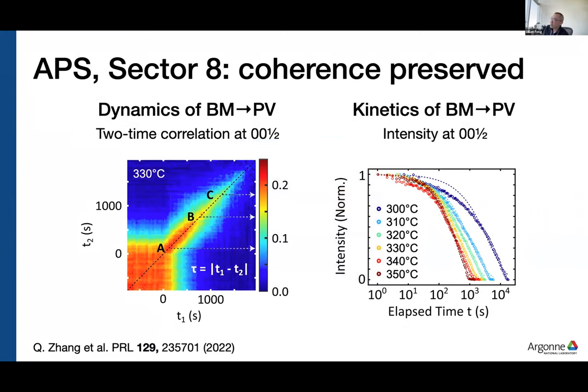And so we did that experiment for our strontium cobalt oxide and strontium titanate at Sector Eight. And so on the left, I'm showing the two-time correlation map where we switched from pure nitrogen to pure oxygen at 330 degrees. And so we are changing from the Brownmillerite phase into the perovskite phase. What I call the dynamics is shown on the left, and the kinetics are shown on the right. So again, the kinetics we already discussed, it's just simply the loss of the Brownmillerite peak as a function of time.